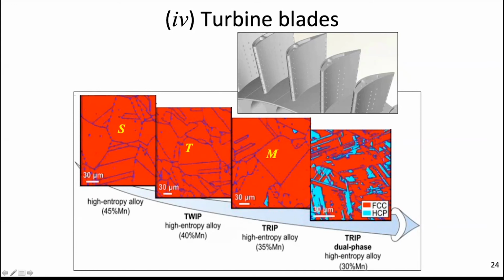For example, the solid solution, the twin structure, or martensitic structure that can give me different textures in the material, twinning so that they can deform properly, or I can make them very rigid at different regions within the same turbine blade. So in addition to the topological benefits, the complexity of the shape of the 3D printed turbine because of the veins that I mentioned earlier, I can also change the strength at different locations and make it high temperature resistant.